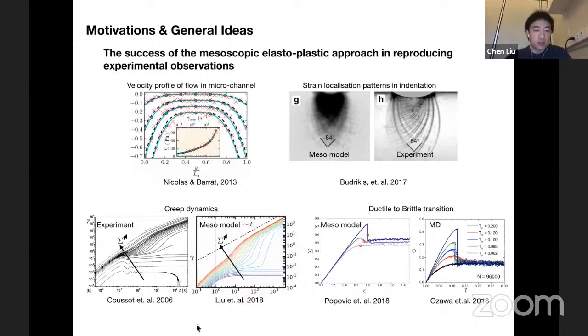The third example is a creep dynamics, where you apply a step stress onto the system. And you can see the response in strain. When you apply small stress, the system just gets stuck somewhere. And when you increase the stress, the system will eventually flow, and in the long time limit, the strain increases linearly with the time. And this is also, so the left is experimental results on some kind of suspension, and on the right is what we produced with the elastoplastic model.